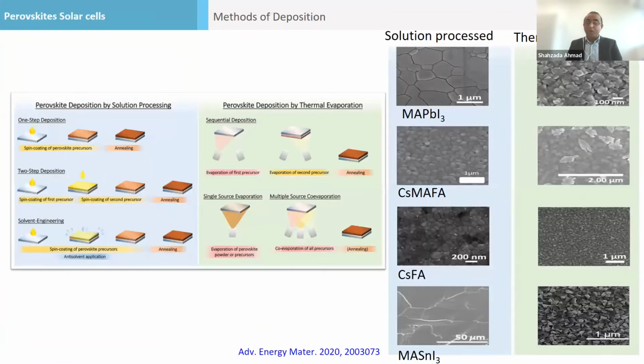What we do is solution processing, but there is another school of thought. There are some people who are doing evaporation or sublimation of the perovskite structure. So we can also do that. You can sublimate, evaporate perovskite molecules and the crystal, and then you can see the microstructure. They form a smaller morphology, but you can precisely control the thickness. This is a good thing about evaporation. This is methylammonium, this is mixed perovskite, cesium, formamidinium, and tin.